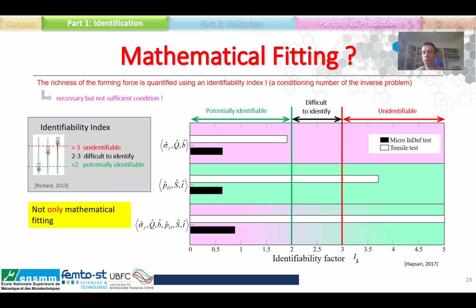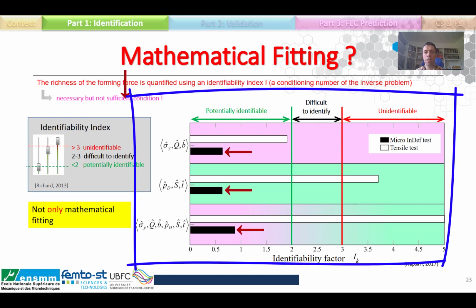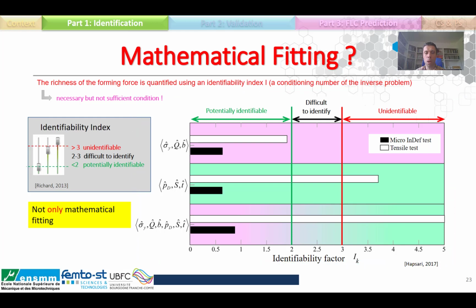If we check the Micro InDef test with the black graphic, we can see that with all parameters, the identifiability stays under 2. That ensures the identifiability with forming forces obtained from the Micro InDef test is the good choice. As you can see, it's possible to identify plastic parameters with the tensile test. It's no longer possible to use the tensile test to identify the damage parameter because the identifiability factor goes beyond 3.